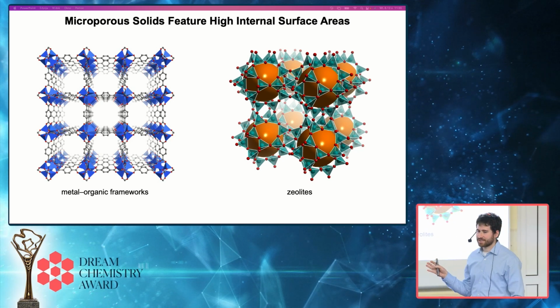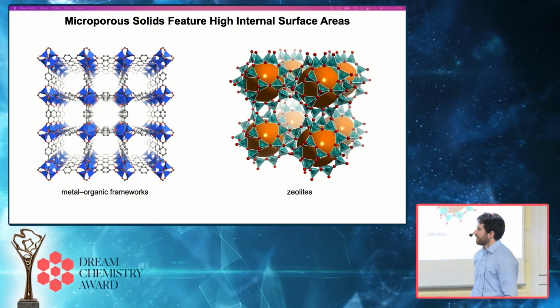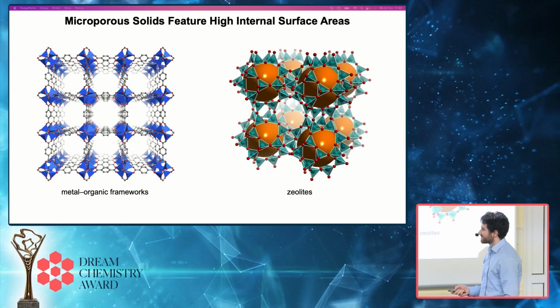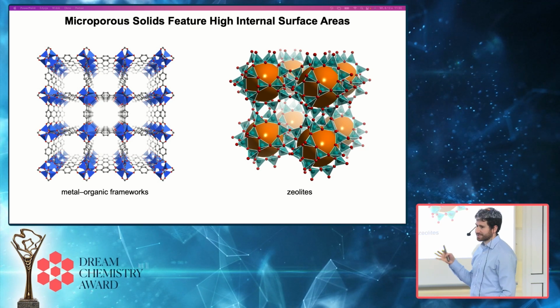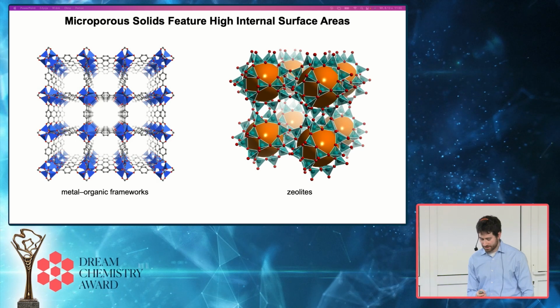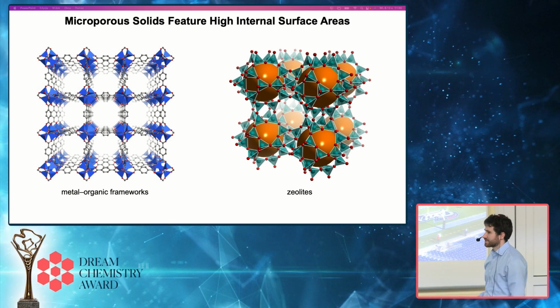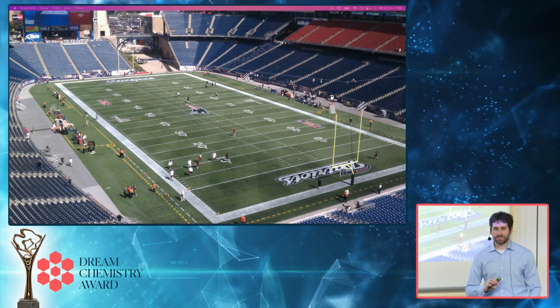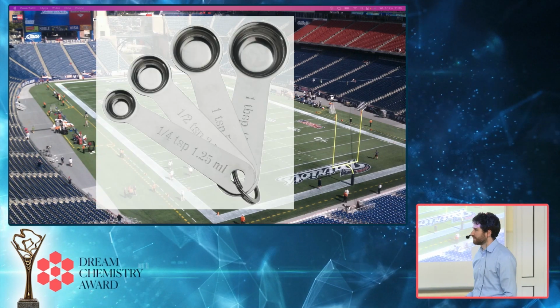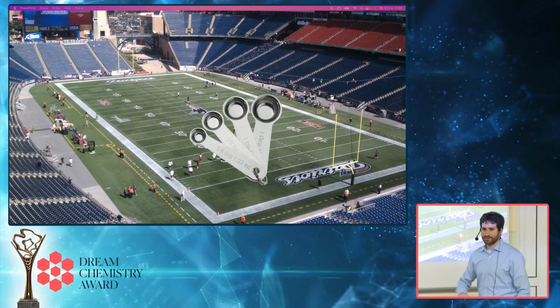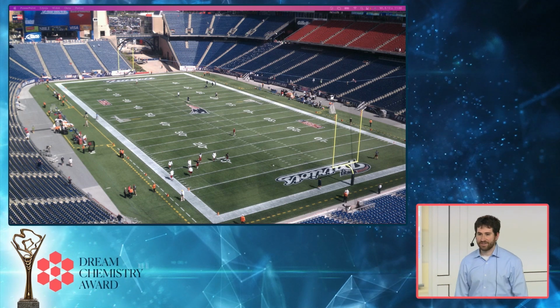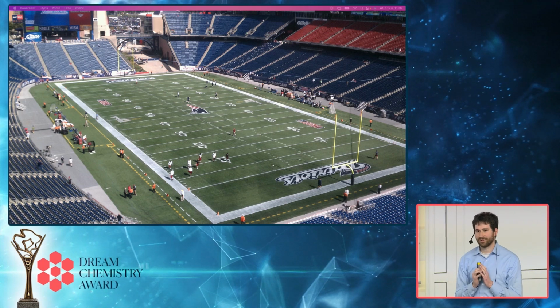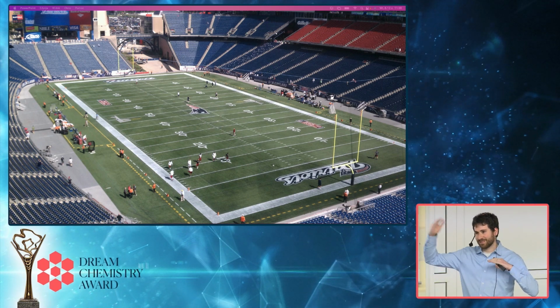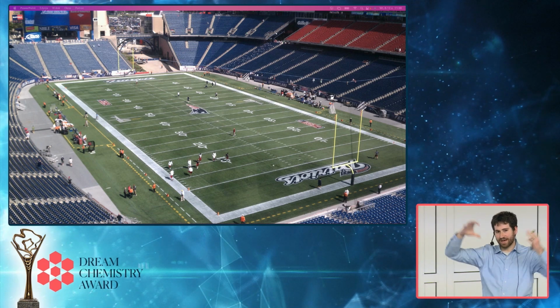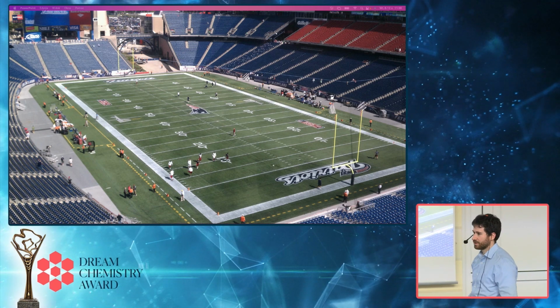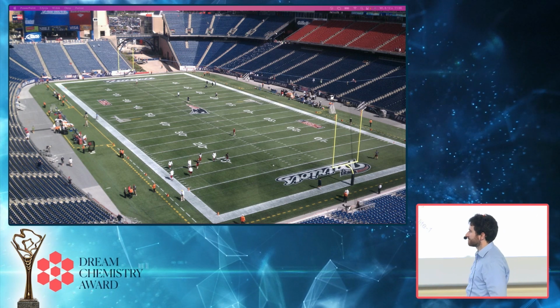Microporous materials are materials that tend to have pore sizes below 2 nanometers. Again, they have a large amount of surface area inside them that can have attractive interactions with gas molecules and can significantly increase the density of gas present compared to the bulk gas phase. Just for some perspective, for some of the highest surface area metal organic frameworks, in just about 2 milliliters of material you can have surface areas on par with those of an American football field or even a European football field as well. This is a huge amount of surface in a very tiny volume of material. And if you have these attractive interactions between gas molecule and surface, you can just imagine the amount of gas you're going to be able to compress and compact inside a material under moderate conditions. This is why these are very powerful materials for storing gases.